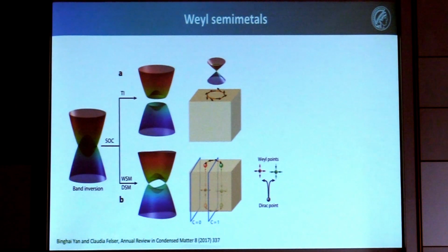So Dirac points are easy to identify because they are at high symmetry points. So the crystal structure should be of much higher symmetry. Then you have these Dirac points, which you find simply if you draw these bands along certain high symmetry lines, which we commonly do in DFT, so you can find them.